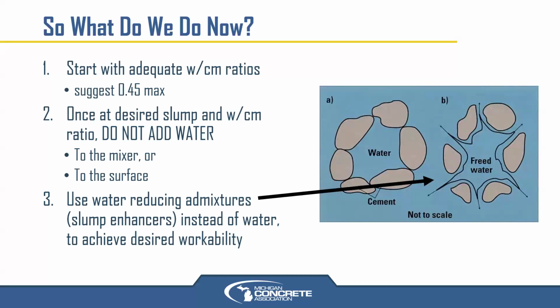All right, you may need to adjust some though. Once you're at your desired slump and water cement ratio, and you haven't exceeded your max water cement ratio for that particular mix, try not to add water. Try not to keep stopping during discharge and add water. I know it's not allowed on most specifications, but I see it all the time on jobs where there are no specifications or there is no inspection. They offload 3 yards to this sidewalk and they go down the road and they offload another 3 yards to another piece of sidewalk of that full load of concrete, and they water it up prior to that next point of discharge. Don't do that.